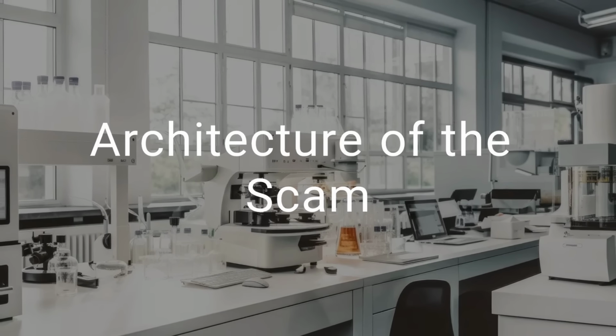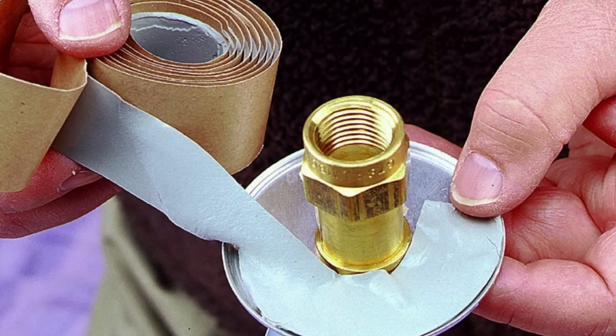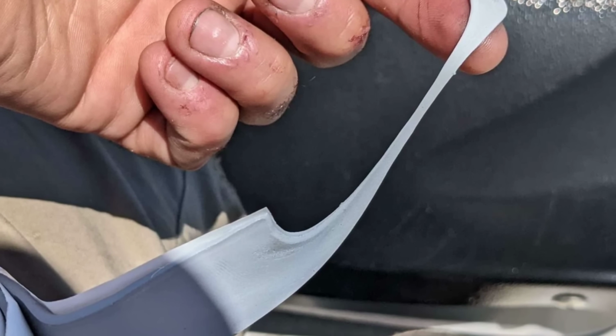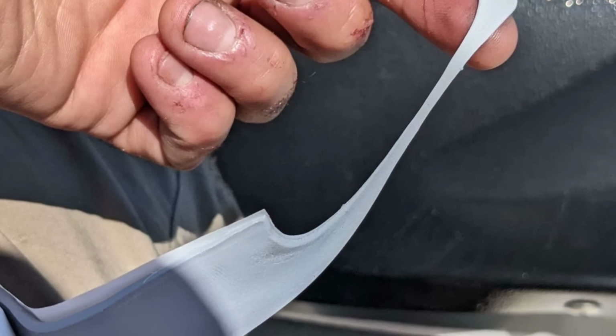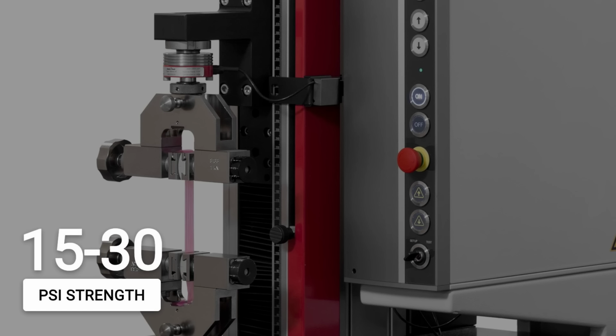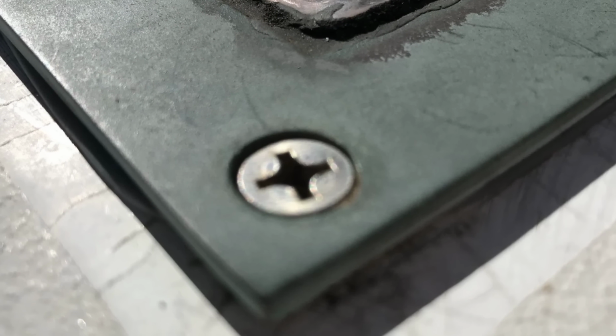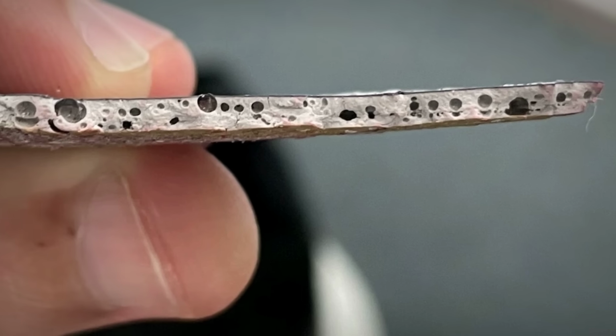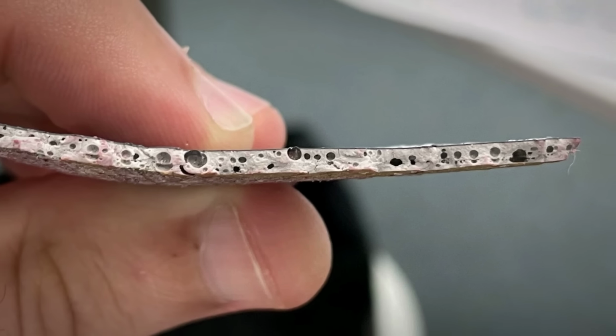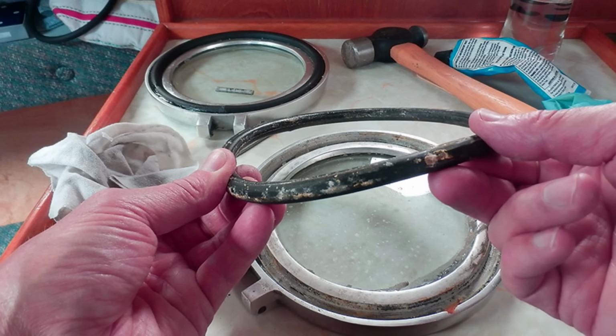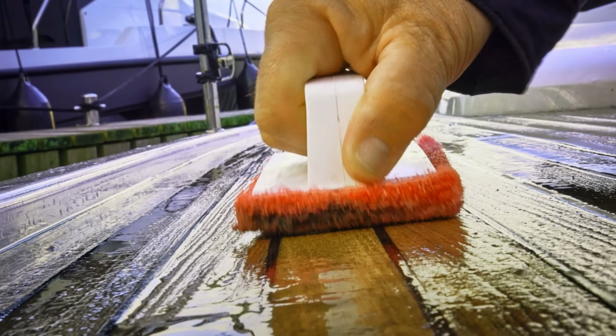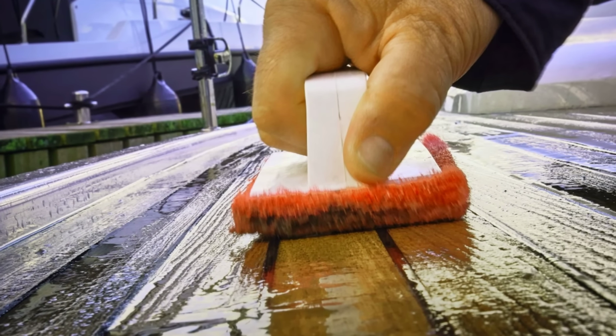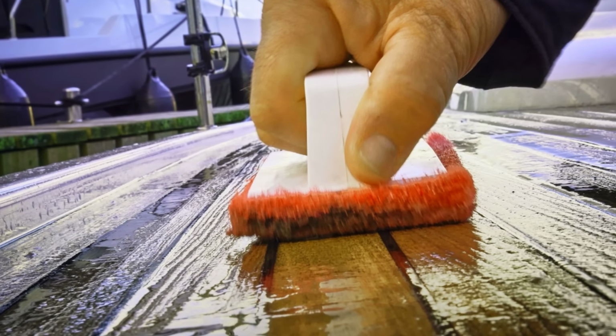Adhesives in the marine world come with bold promises, but their true character is found in chemistry and numbers. At one end sits butyl tape, a non-curing petroleum-based gasket material. It is inert, it never hardens, and it does not form a chemical bond. Its tensile strength is barely 15 to 30 pounds per square inch, but that is beside the point. Butyl's job is to create a flexible, serviceable gasket that compresses under pressure and stays pliable for decades. When it is time to rebed hardware, you peel it away, wipe the residue, and start over. No solvents, no chisels, no drama.